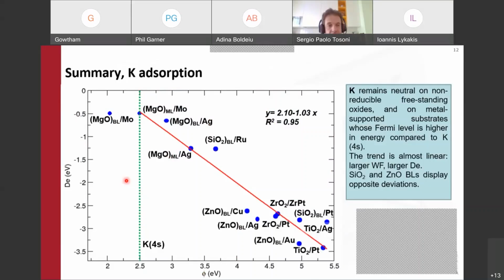So what happens if we start increasing the work function of our substrate? It means that an acceptor state gets deeper and deeper in energy until the point that it is at a lower energy compared to the 4s orbital of potassium, and this is more or less where you should expect the charge transfer to take place. Of course, it's a very rough approximation because this is just an initial state. Then during the calculation, the wave function will relax, so the relative energy of the orbitals can change. But as you can see, it sort of holds true and explains the whole picture.